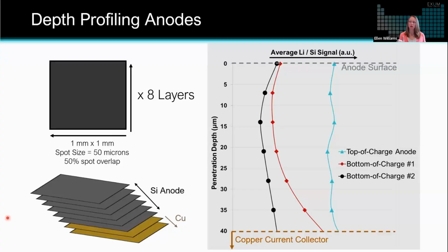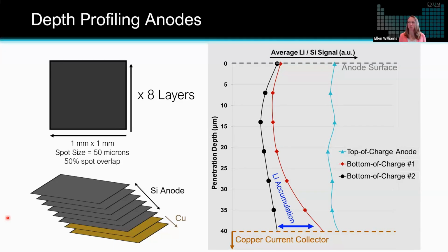But then when we look at the bottom of charge anodes, there is still lithium in these bottom of charge anodes. So that suggests that we've got some amount of non-recoverable lithium tied up in the SEI. Potentially, on the surface, there may be some electrolyte decomposition that's occurring. But what distinctly was different about the 2 samples was once we got deeper into each of the samples, we see quite a bit of difference in how much lithium there is, even though they both started out in the few surface layers in a very similar amount. So clearly we're getting some lithium accumulation that is different between those 2 samples, where again, the only difference between them is where they were pulled from the cell.